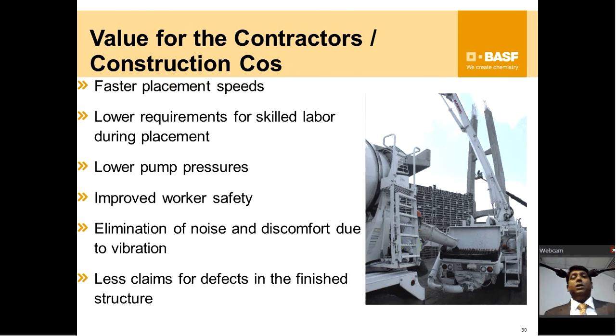Lower pump pressures. Your pump pressure is much lower, which means, we have been working with swing stator for the last 5-6 years, especially on self compacting concrete and other things, where there is now a very clear understanding, or we now have data. What it says is that, compared to a traditional vibrated pumpable concrete with 100 to 120 mm slump, versus an SCC or an SDC, for every 20,000 or 30,000 cubic meters of concrete, the pumping line needs to be changed because the abrasion is much higher on the pumping line.